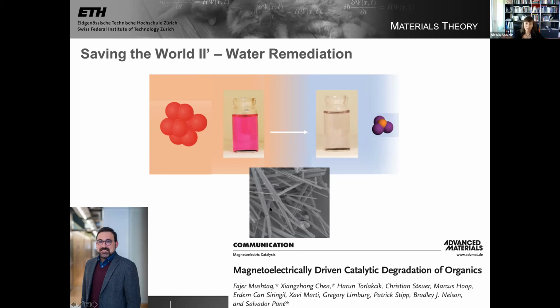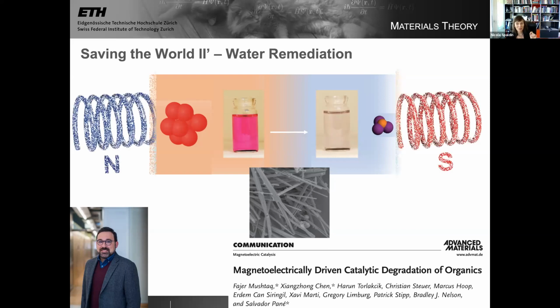You can see, not beautiful, pristine, thin films of bismuth ferrite, just bismuth ferrite nanoparticle crystallites, or micron size, I think, crystallites. And when he did that, he found that the bismuth ferrite broke down this nasty molecule into its constituents, into small molecules like methane and carbon dioxide and water, which are not toxic. And we think that the mechanism is very similar for the water remediation, as I showed you for the water splitting. What was nice, I'm not sure that it's useful particularly, but I think is rather cute, is that this process can be strongly accelerated using magnetic fields because of the multiferroic properties of bismuth ferrite. So this was also a kind of nice feature. It's maybe not particularly useful, but it was kind of fun.